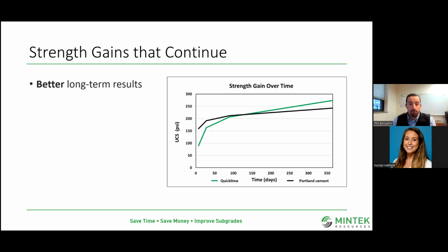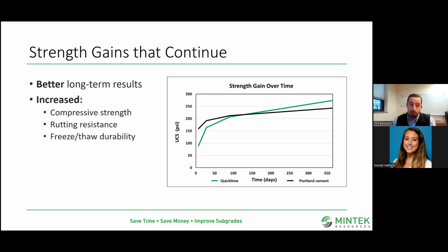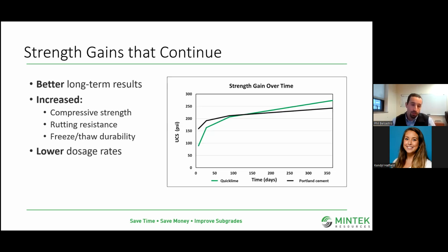So really, what's that going to do for us? Those long-term results, better strength, rutting resistance, freeze-thaw durability. We're going to create a nice solid monolith that's not going to allow any moisture absorption and any shrinking and contracting that might come with those seasonal changes. Those lower dose rates, lime, you can allow for lower dosage rates to achieve those better long-term results.